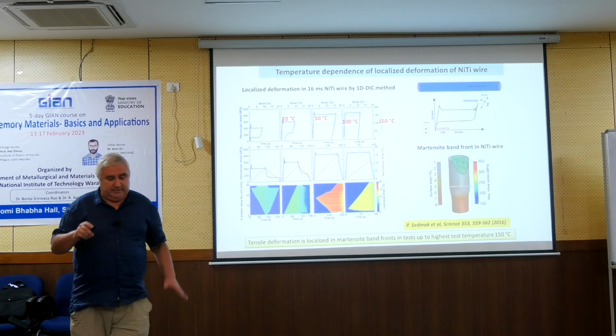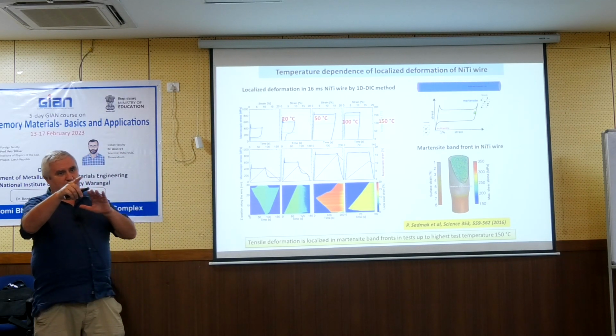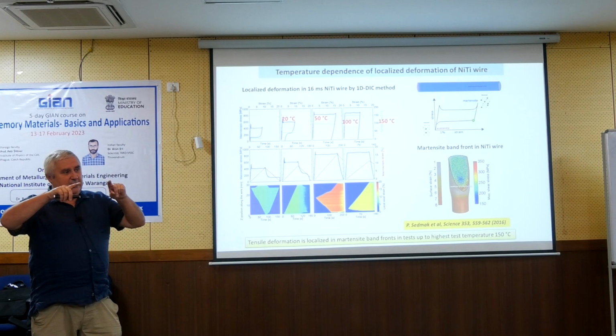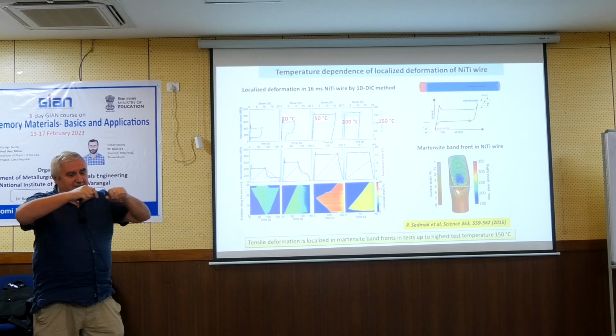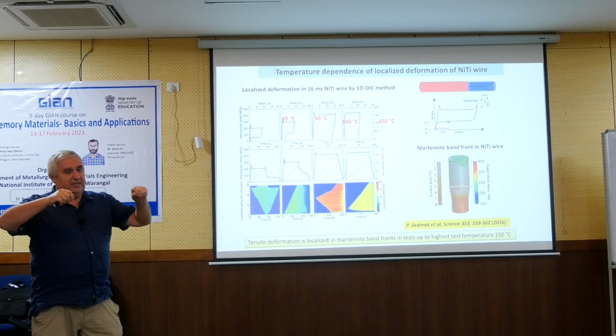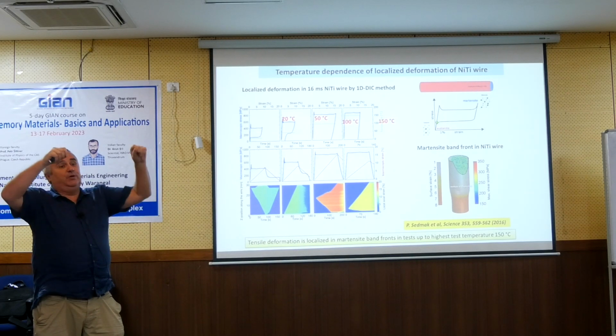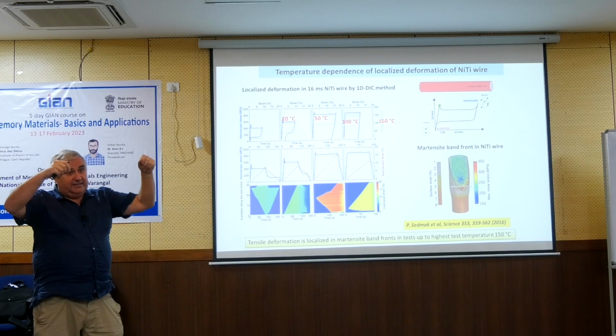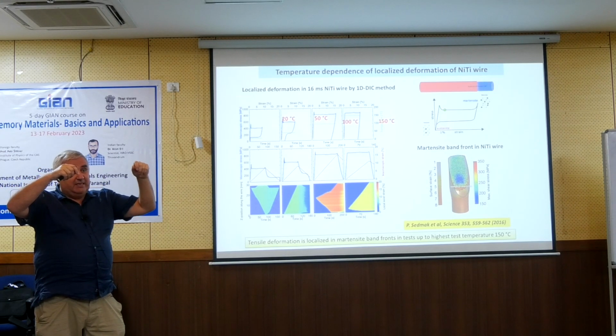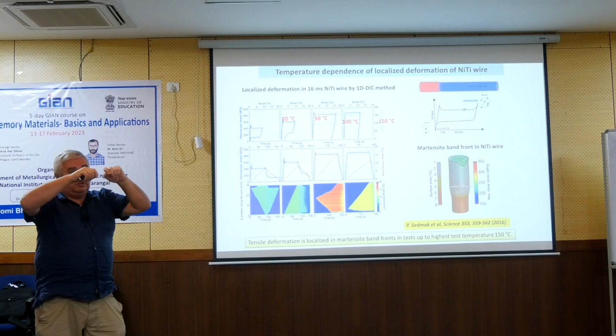Just to answer the first question. The loading when the Martensitic transformation occurs is rate insensitive. But if you do it at high temperature, 200 or 300 Celsius, it's rate sensitive. So it depends whether you do it in load control or strain control.